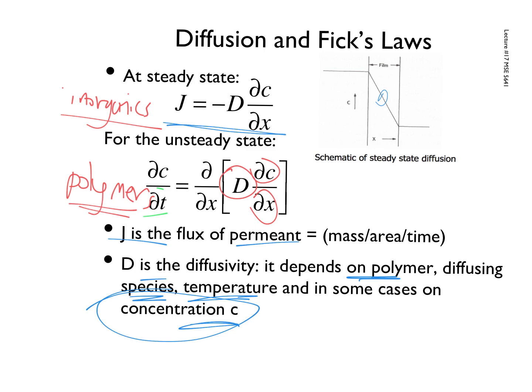All right, that's why this expression exists, because D is not a constant in these systems. And hopefully that makes some sense based on what I showed you a few minutes ago. We talked about PMMA, how much it loves CO2. At 9 cc's per cc of PMMA, it is not just a solid matrix of PMMA anymore. It's this weird blend of CO2 and PMMA. And so the diffusion coefficient of that structure is nowhere near what it would be for pure PMMA alone. What that means is what is diffusing can trigger additional diffusion. Okay? Hopefully that makes some sense, again, thinking about that very extreme example.